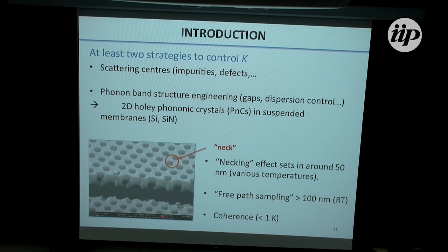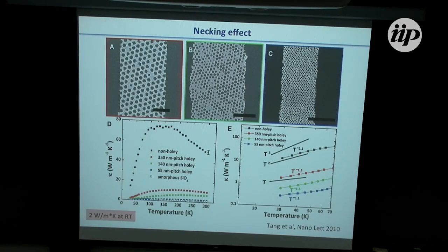There are different approaches to study that. And one of the heated debates has been whether we do have coherence effects in phononic crystals. So the neck effects came about when this type of two-dimensional phononic crystals were studied. These are fairly disordered, or you can describe them as a mesh. And the thermal conductivity was measured here as a function of temperature for membrane-like structures and different separations of holes, and compared to this little line with open squares, which is the amorphous silicon oxide regime.